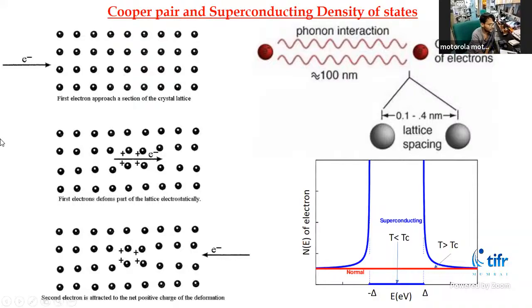Very low temperature. So at low temperature, what happens? These atoms will be stabilized in their positions. When an electron comes, it will distort these atoms, forming a positive charge, which we call a phonon. So the first electron coming into the lattice will distort these atoms and form a phonon, and the next electron, coming with opposite spin and momentum, will see this phonon, and this will form a Cooper pair. So electron, phonon and electron, this bonding is called a Cooper pair.